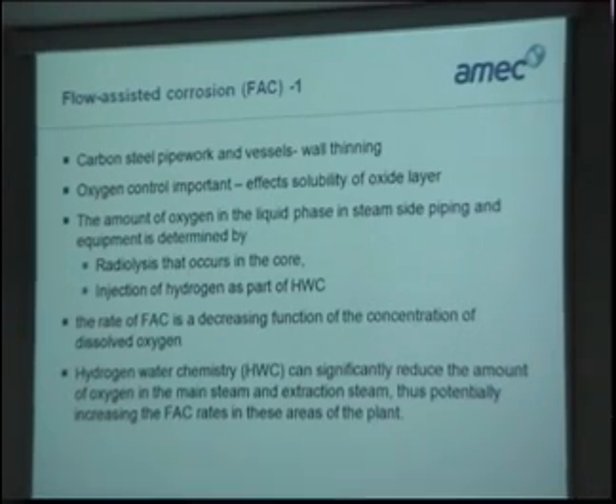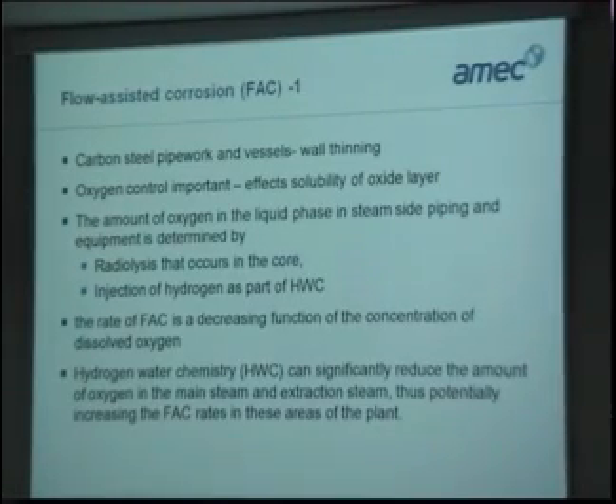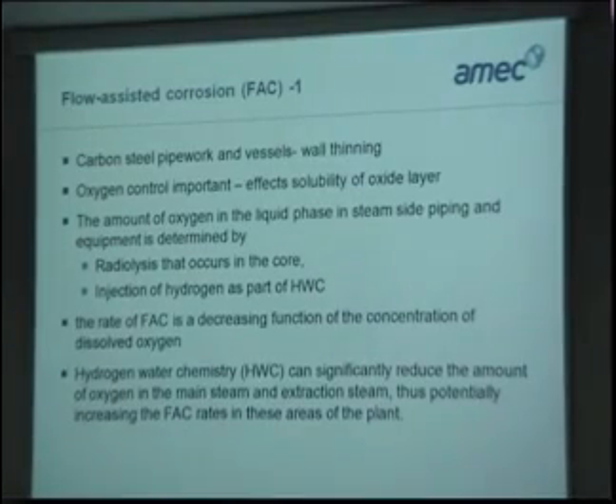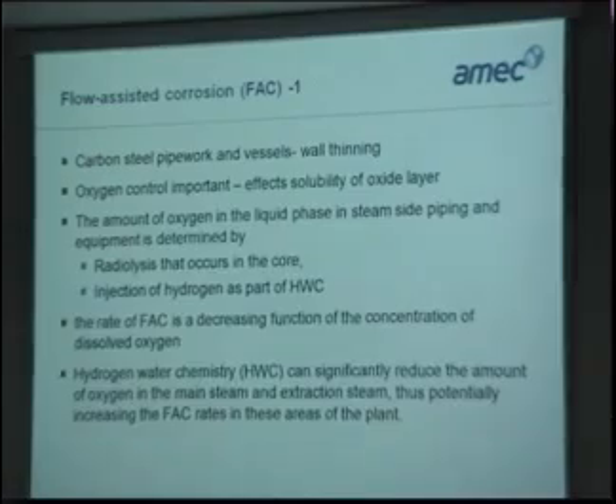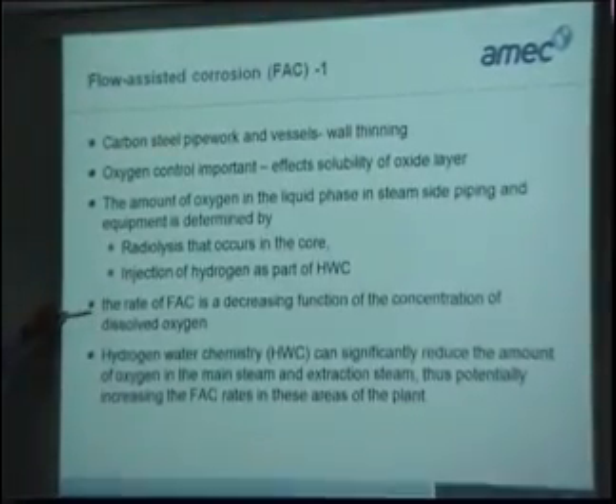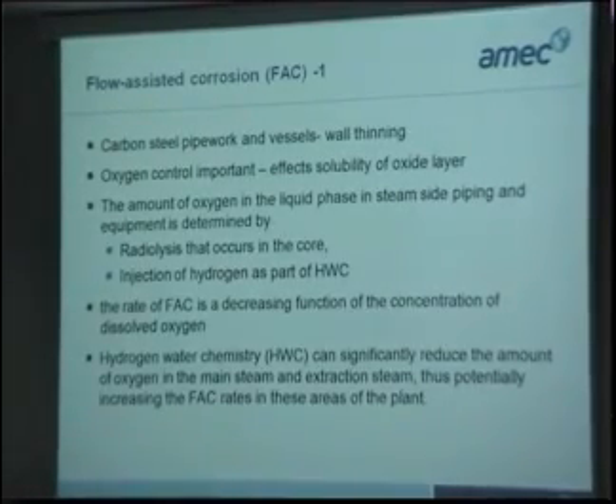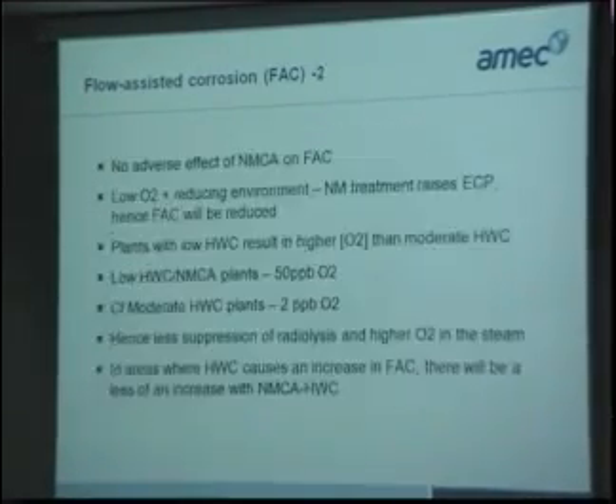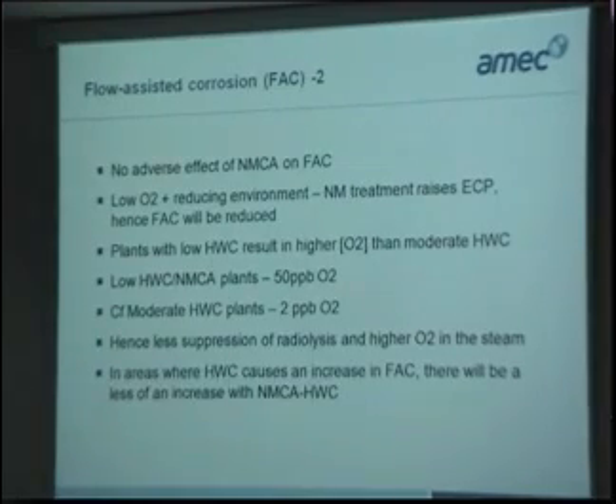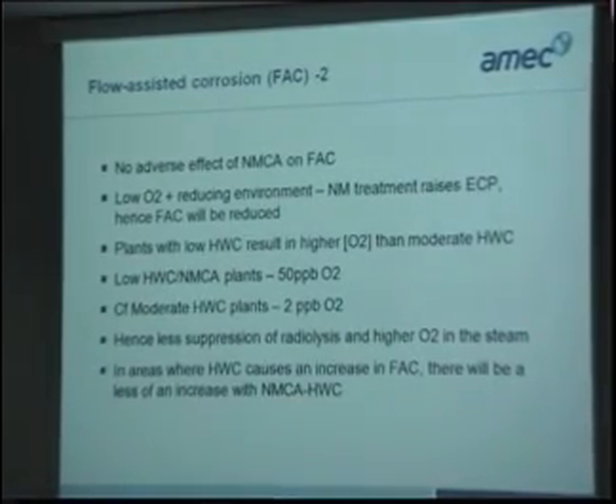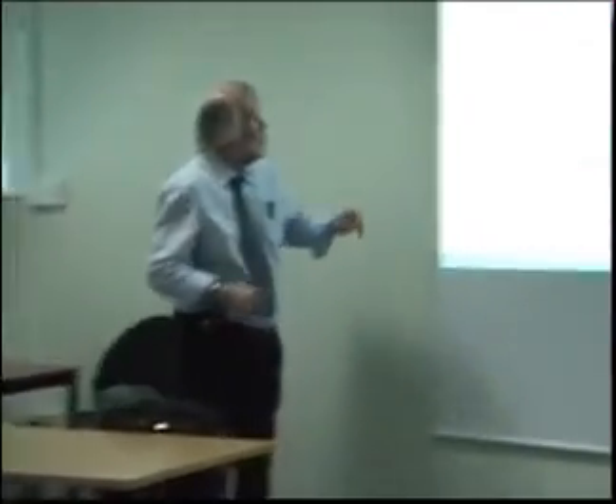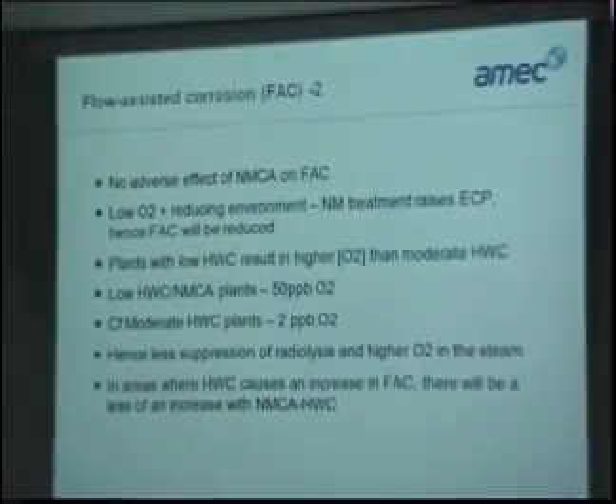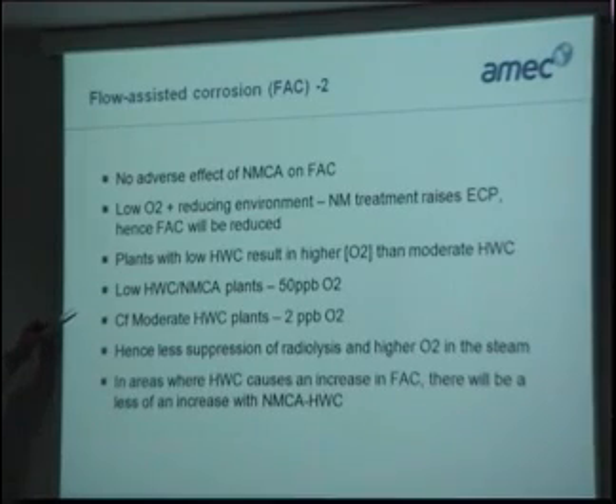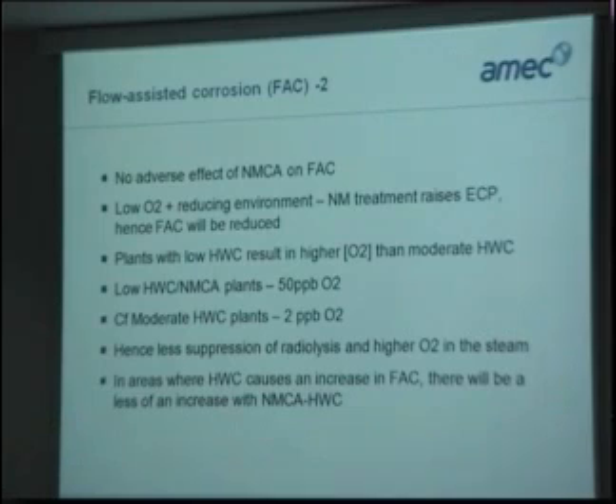Flow-assisted corrosion is another aspect. And again, we're looking at hydrogen water chemistry, reducing the amount of oxygen in the steam. But that potentially could increase the flow-assisted corrosion rates, because unfortunately you have an inverse relationship between the rate of flow-assisted corrosion and the concentration of dissolved oxygen. However, the use of noble metal addition didn't have any adverse effect on flow-assisted corrosion in practice. And we've got plants with low hydrogen water chemistry resulting in higher oxygen. Comparing low and moderate hydrogen water plants, there's at least an order of magnitude difference in the oxygen, hence less suppression of radiolysis and higher O2 in the steam.